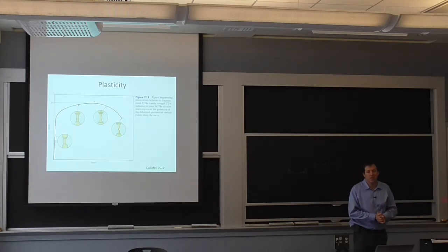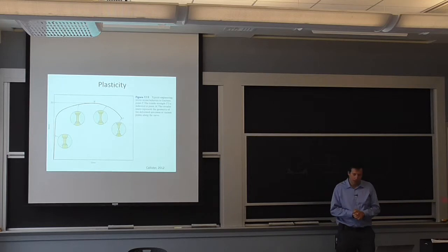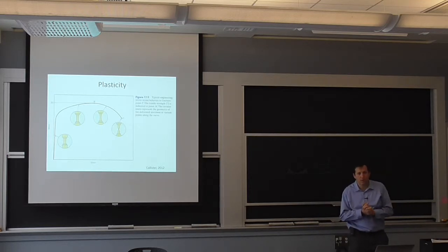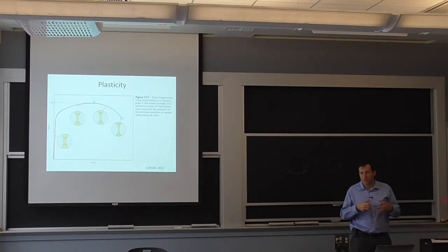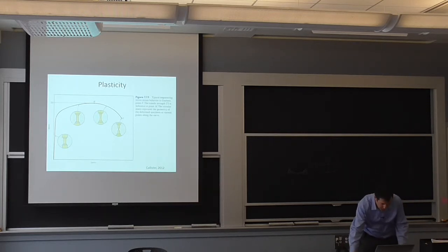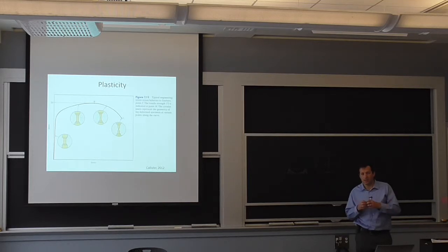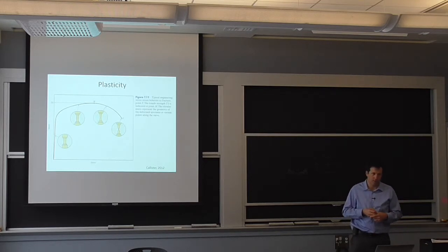There's a lot of implication for that. If anybody in the class eventually does finite element analysis of any kind of structure where you can include this behavior of the metal when it starts deforming plastically — so you do a non-linear analysis and include all this behavior — you don't want to include this curve as is, because this is not a representation of the actual material. When you start deforming locally, it's continuing to get stronger, but you have a shorter cross-section at that point.